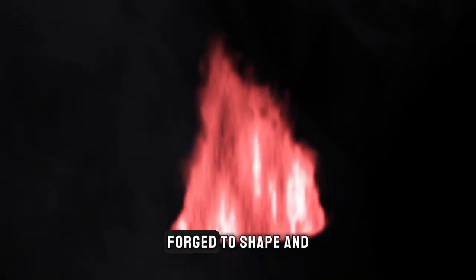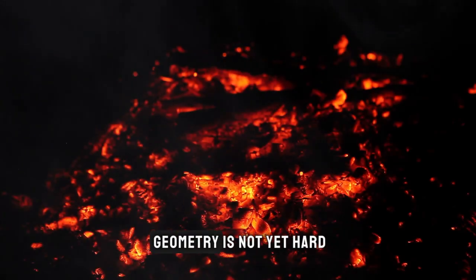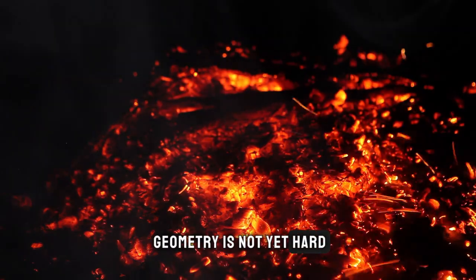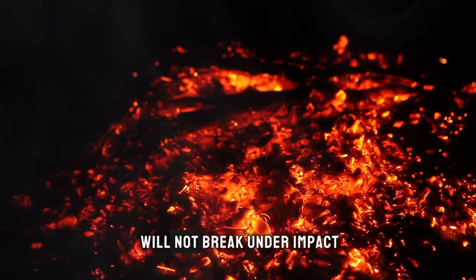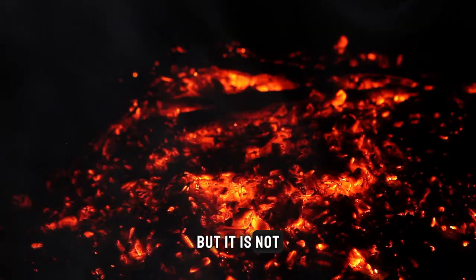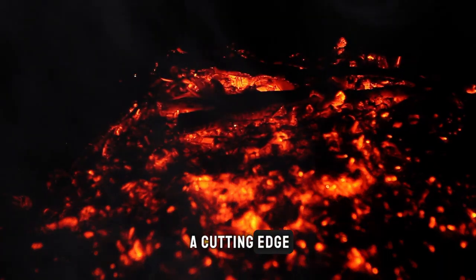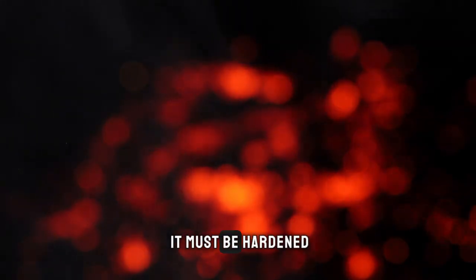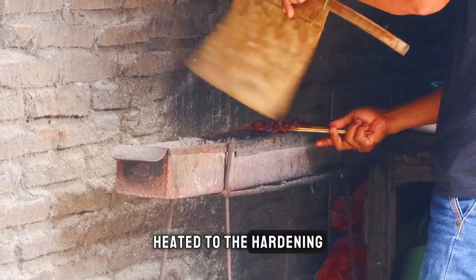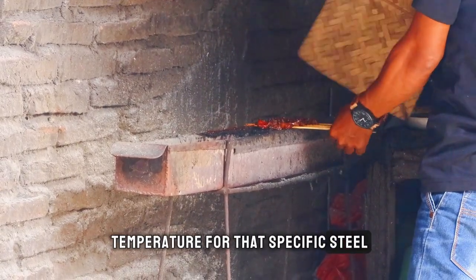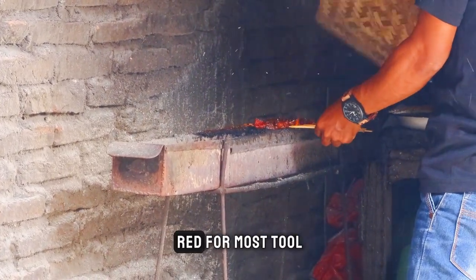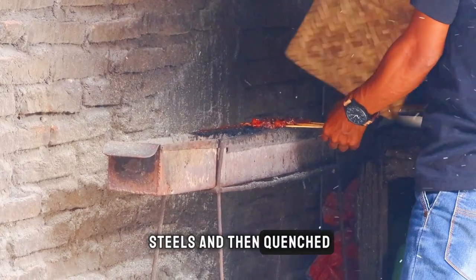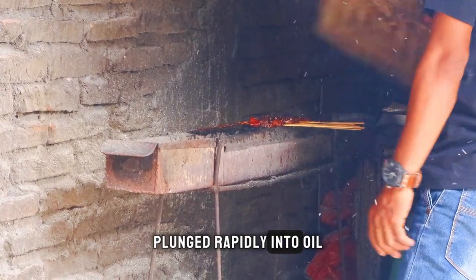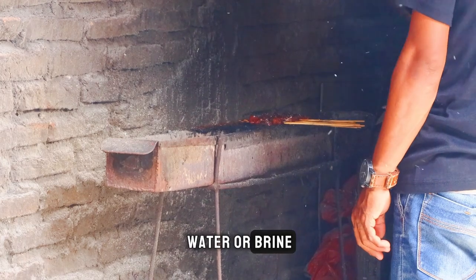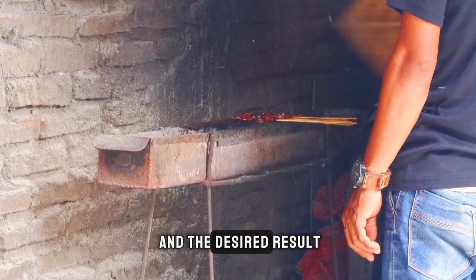A tool made from high-carbon steel, forged to shape and ground to its working geometry, is not yet hard. It is tough, it will not break under impact, but it is not hard enough to hold a cutting edge. To make it hard, it must be hardened, heated to the hardening temperature for that specific steel, typically a bright cherry red for most tool steels, and then quenched. Plunged rapidly into oil, water, or brine, depending on the steel and the desired result.